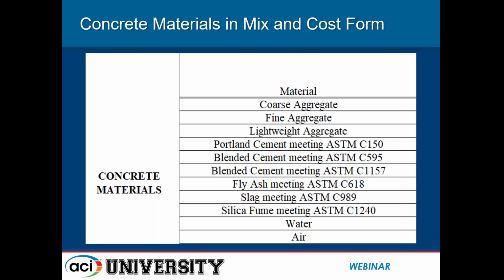Coarse aggregate, fine aggregate, which includes a silica sand, lightweight aggregate, Portland cement, blended cement meeting either ASTM C595 or C1157, fly ash meeting ASTM C618, slag meeting ASTM C989, and silica fume meeting ASTM C1240. You will need water in your concrete mix, and you are allowed to add air to your concrete.